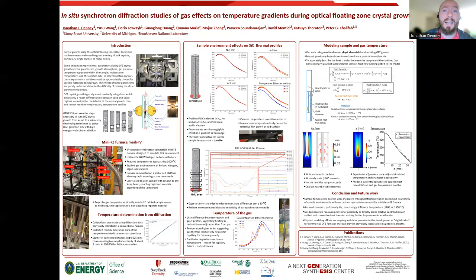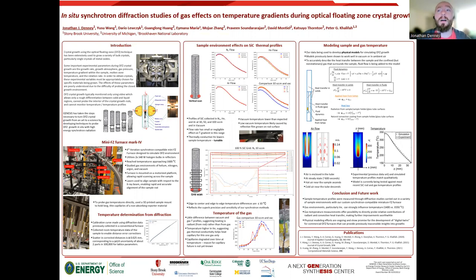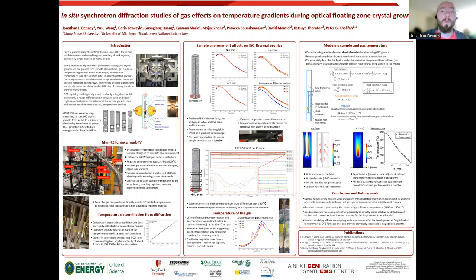The exact temperature behavior in the system is poorly understood, so we have developed ways of probing the temperature profiles on the feed rod with x-ray diffraction. I've designed up to now a Mark IV mini OFZ furnace that is synchrotron compatible and can be operated under a variety of gas conditions. Temperatures are extracted via refinement of lattice parameters.